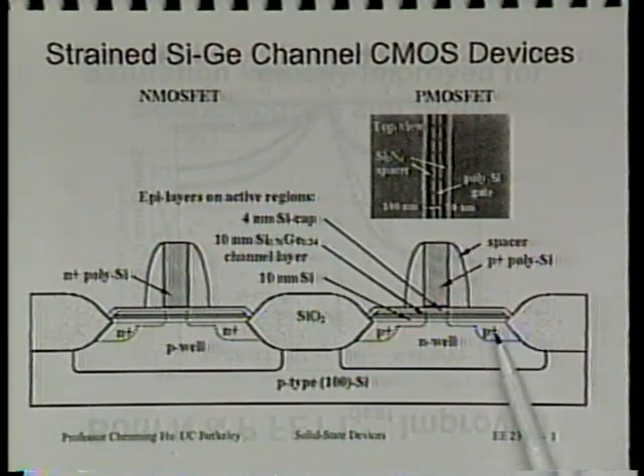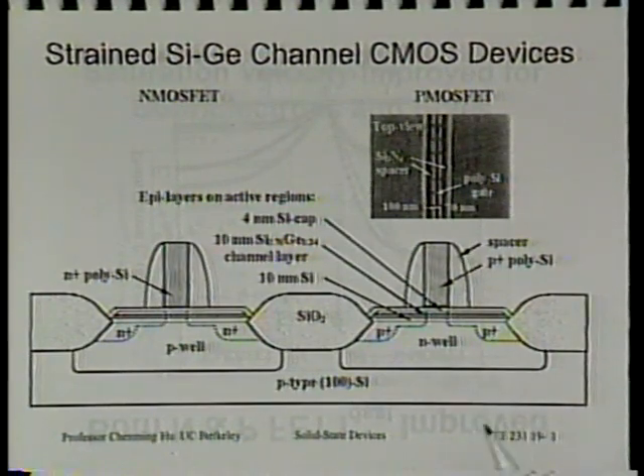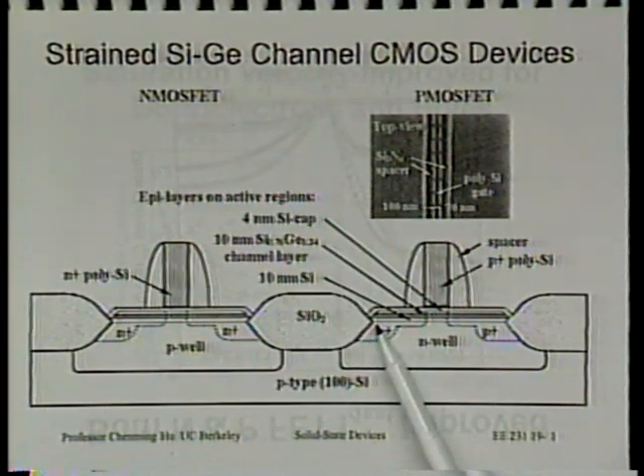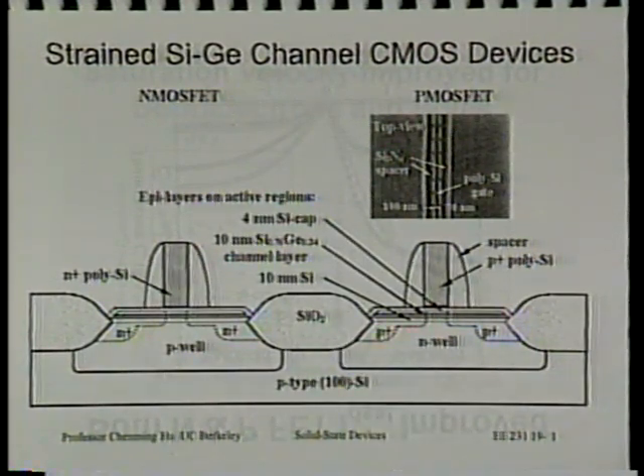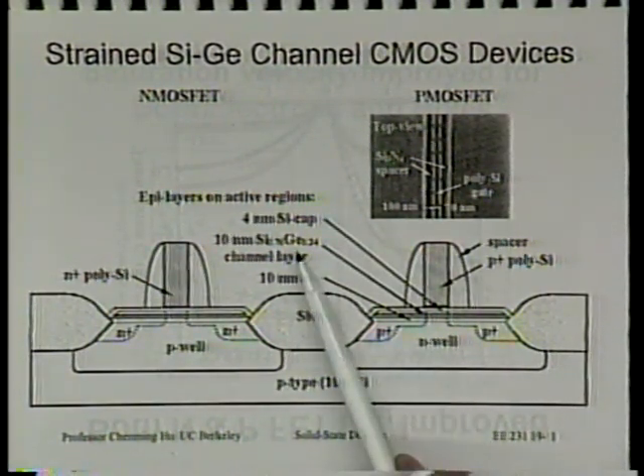At a point, in a normal process, you would just be growing gate oxide, right? But instead of growing gate oxide, at that point you grow an epitaxial layer of very thin silicon. Now that actually is optional. It just so happens that when you put the wafer into this epi reactor, it's better to first grow some silicon rather than growing silicon germanium. Growing silicon first is a little easier, gives you a clean surface, and then you grow silicon germanium. Okay, so that's a minor consideration. And then you put down a thin layer of silicon germanium.